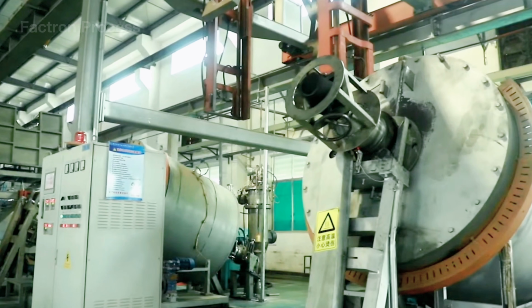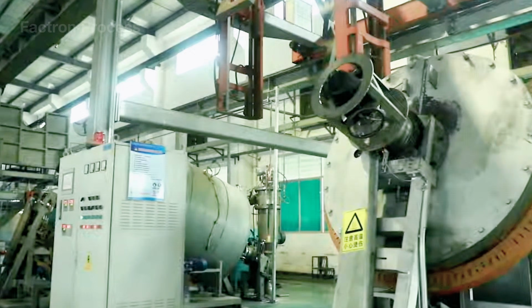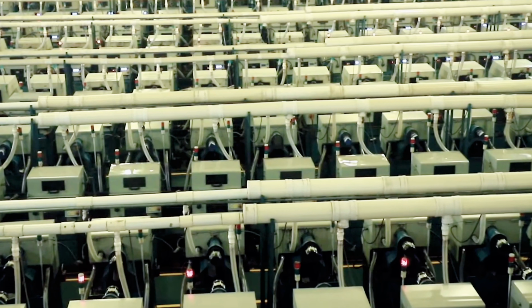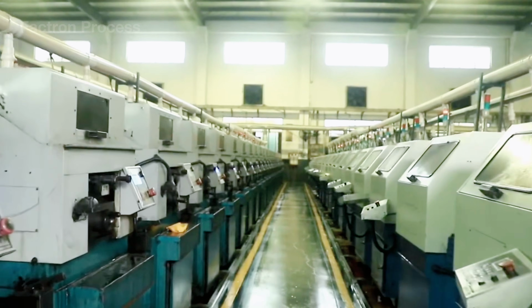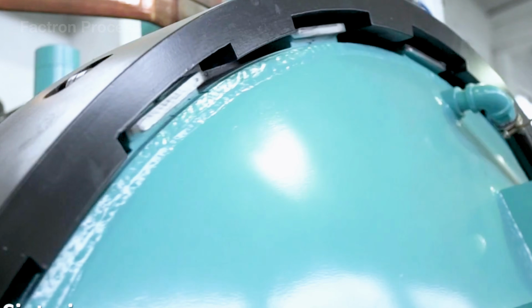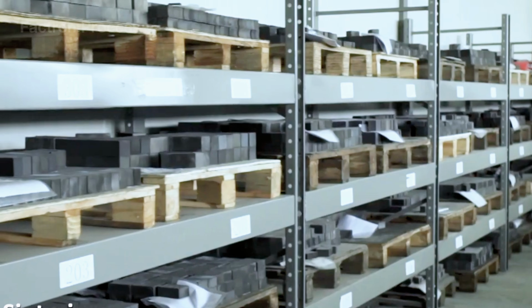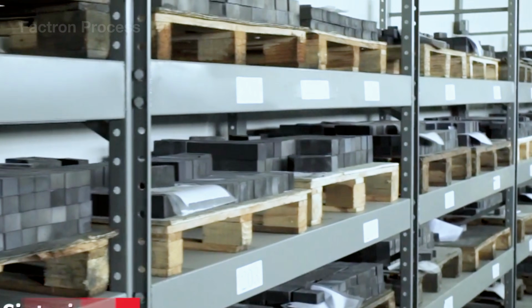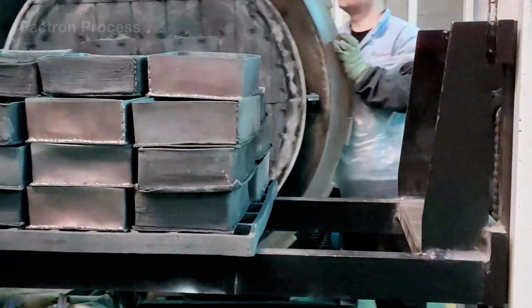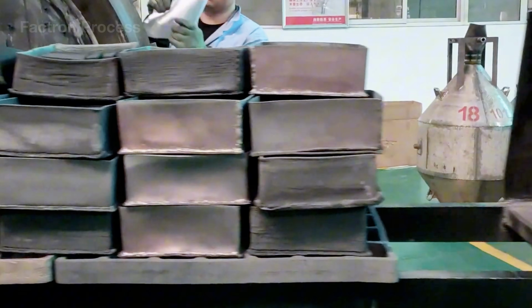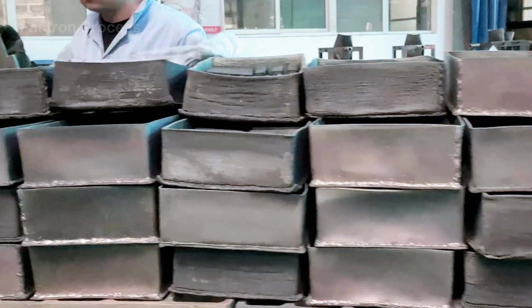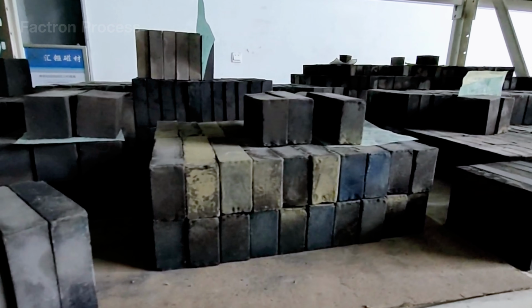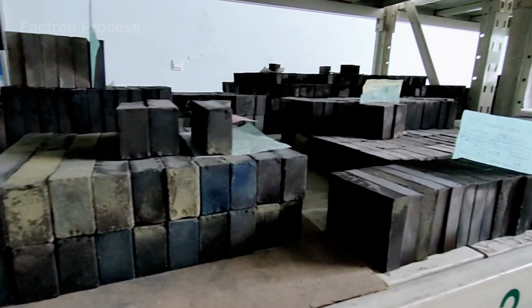The blocks are placed on molybdenum trays and vacuum sintered at 2200 to 2400 degrees Fahrenheit. Over 4 to 5 hours, the neodymium-rich phase helps bond the particles, causing shrinkage and bringing the compact close to 100% theoretical density. Finally, it is cooled under controlled conditions and tempered at approximately 950 degrees Fahrenheit to improve coercivity and stabilize the microstructure.